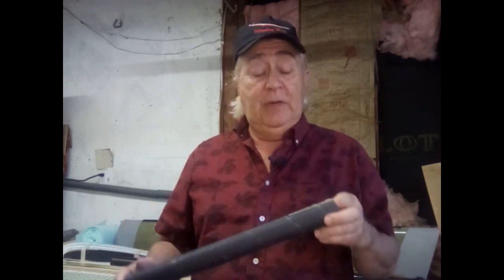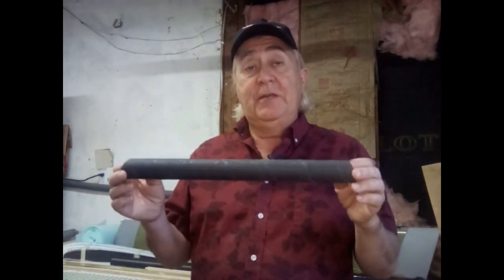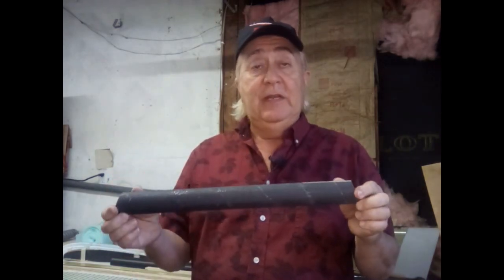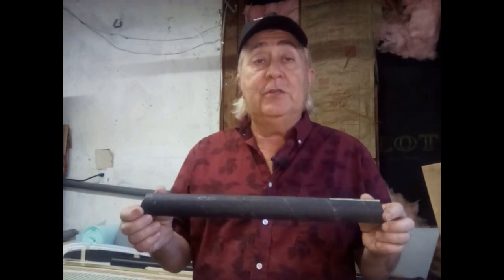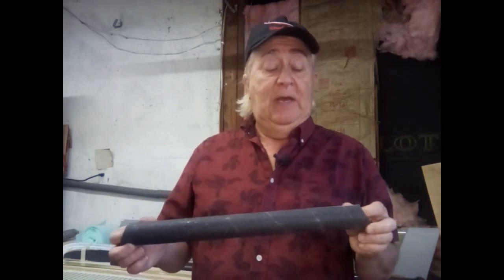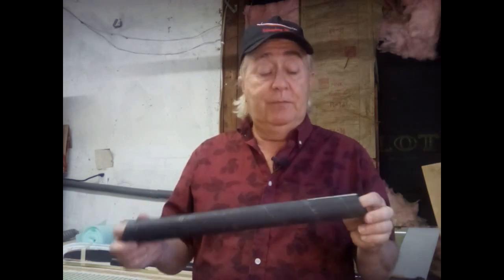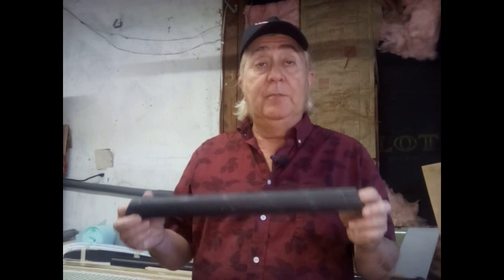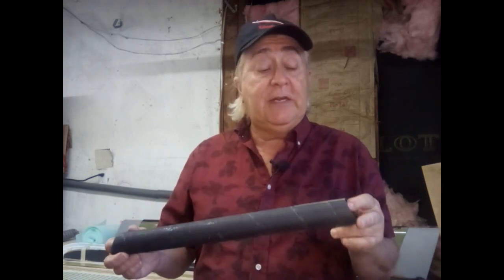And that's because of another problem. By the time I took this tubing down to the same strength as aluminum tubing, I'm going to run into what's called its buckling limit. And buckling limit is a heck of a problem that we deal with in ultralight composite structures, or ultralight structures of any kind, is that now the structure is strong enough in tensile strength, compressive strength, bending strength, strong enough in all of those, but it'll buckle. And once it buckles, all the strength's gone. Poof. And that's a problem.